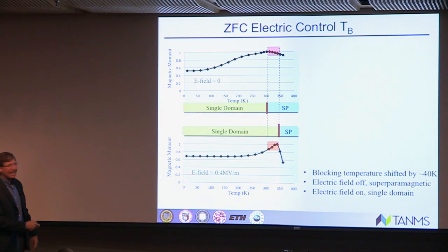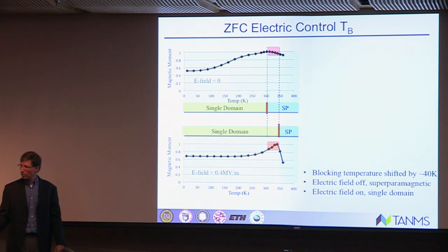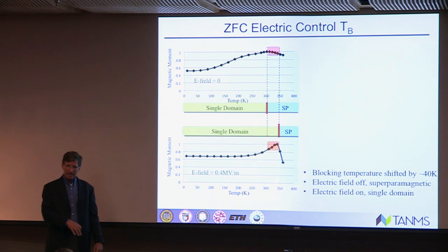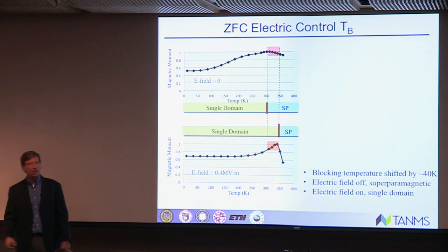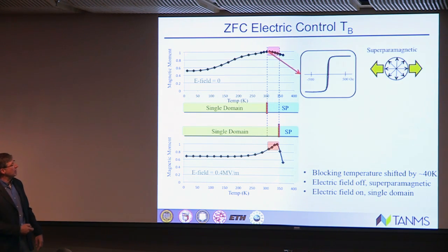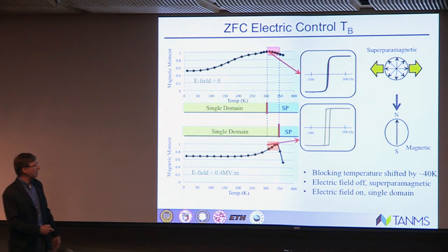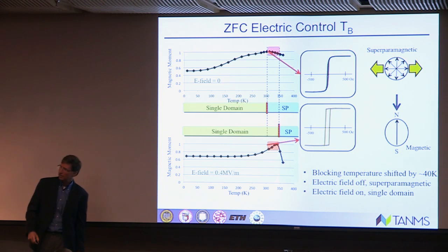Now down here is that same sample, same measurement, but now we applied an electric field. Now what you'll notice is up here TB is around 300, down here TB is around 340. So we shifted the blocking temperature by about 40 degrees Kelvin. Or another way I like to put it, at room temperature we have superparamagnetic behavior. If we apply an electric field, we can actually stabilize that and have single domain.